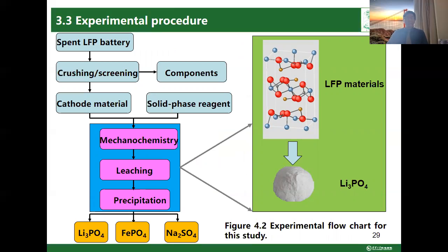This figure in this slide is the experimental parameter flow chart for this study. In the following description, I name the lithium iron phosphate cathode material as LFP material, and the solid phase reagent sodium persulfate is named PS agent. The cathode material powder and some of the co-grinding agent were first put into a zirconia ball milling jar along with eight zirconia balls with a diameter of 8 millimeters.